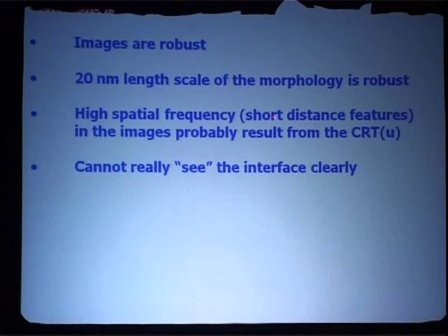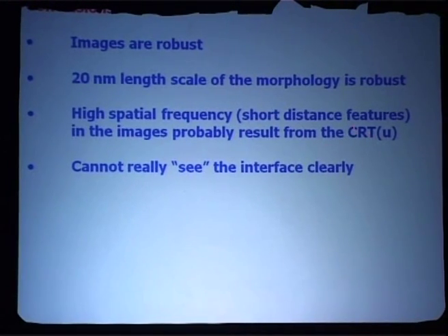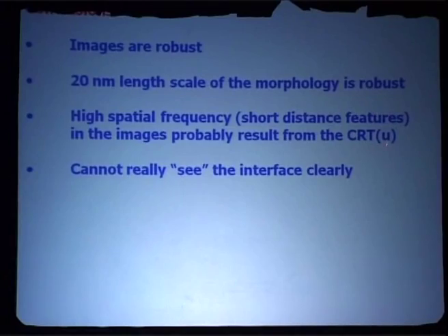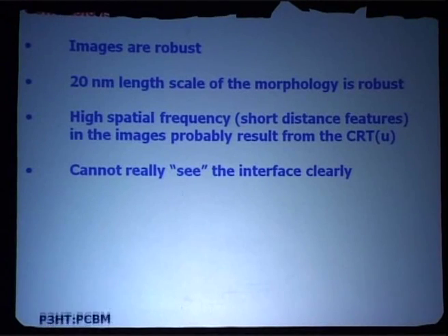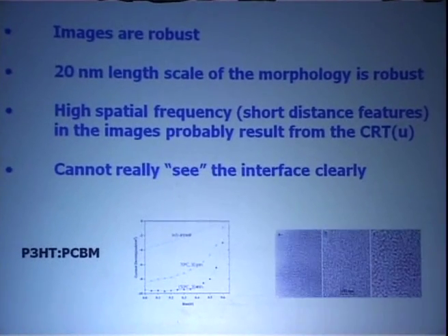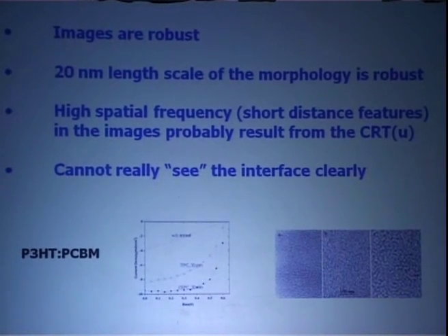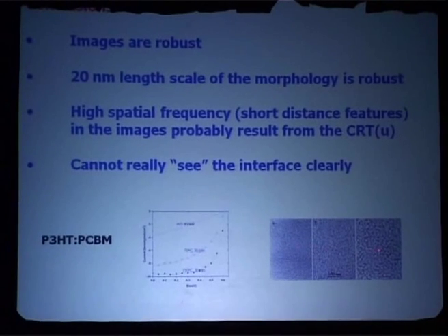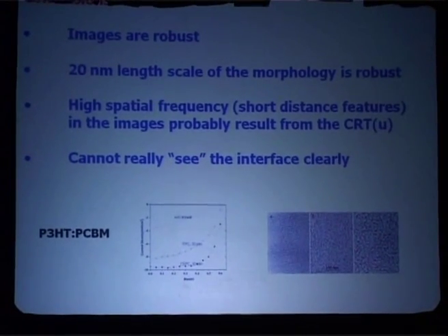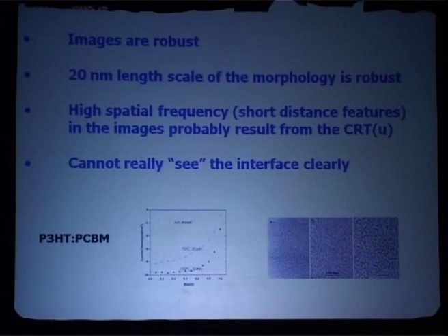High spatial frequencies you're never going to see because at those length scales, the contrast transfer function is not sensitive. And there are a lot of other reasons why we have confidence. Just by annealing the sample, one sees these changes, as I said before.